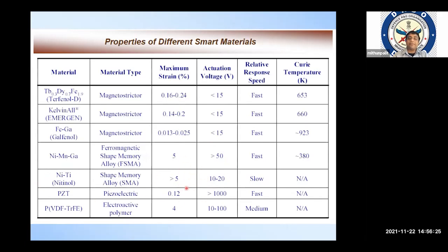Nitinol, the shape memory alloy, also gives very high strain, and it has a very moderate voltage requirement. However, nitinol is a thermally activated system, so it always has some hysteresis. That means the temperature of phase transformation while heating and while cooling is not the same. Therefore, every cycle the material is left with some residual deformation strain, and this strain will slowly build up, decreasing the total cycle life of the material.